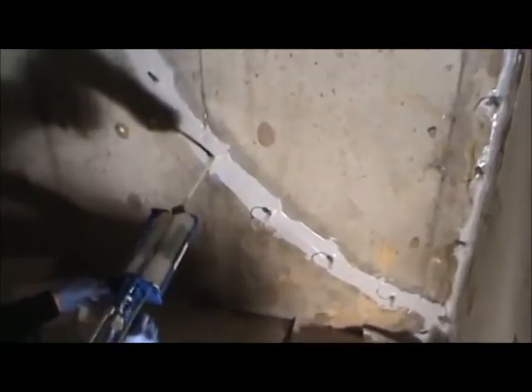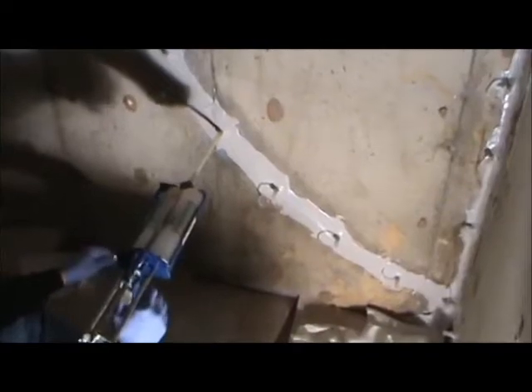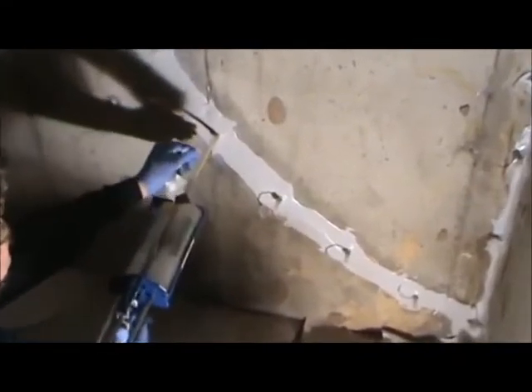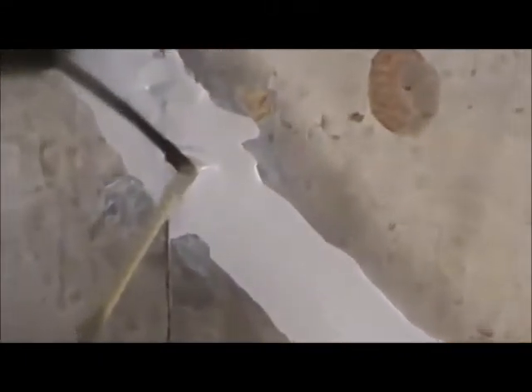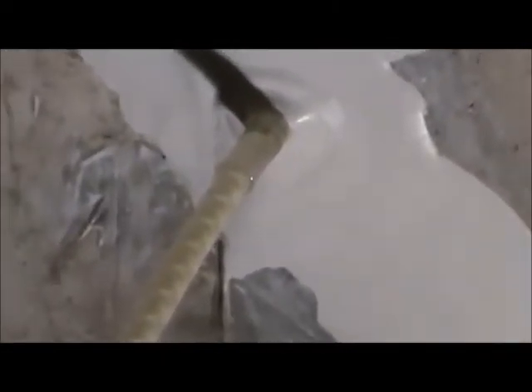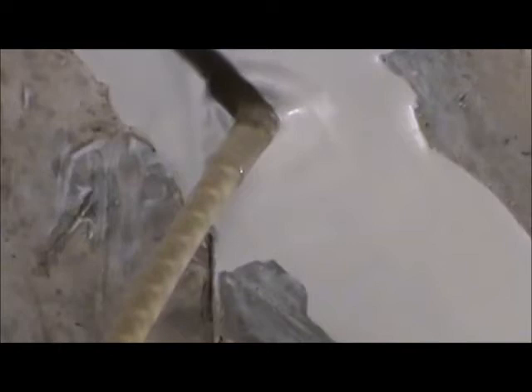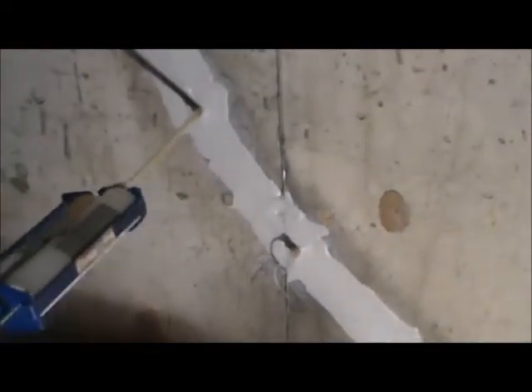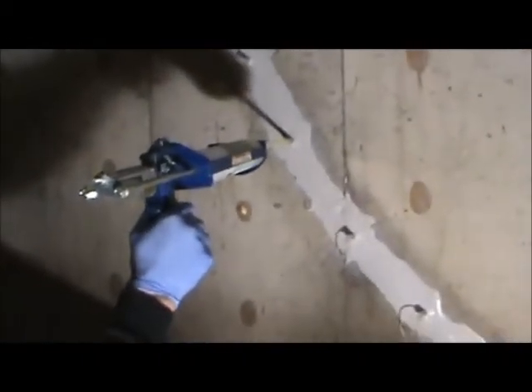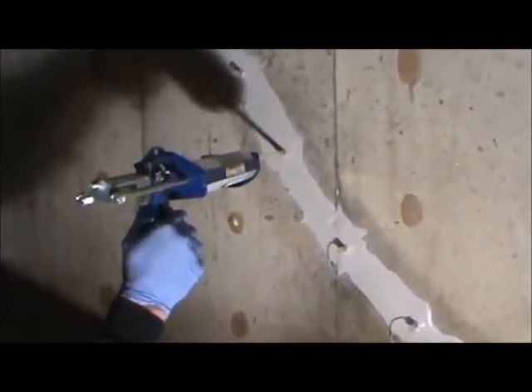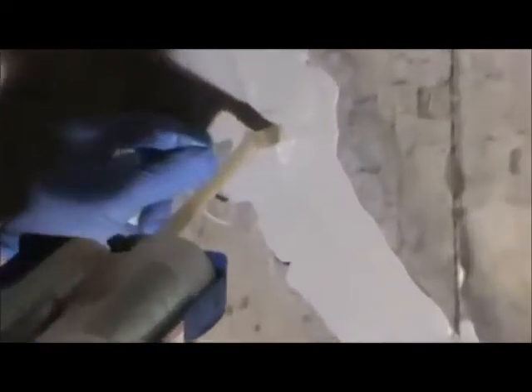Residential concrete has a compressive strength of around 3,000 psi with an internal bond strength of under 400 psi. 1001 injection epoxy has a compressive strength over 14,000 psi and an internal bond strength of approximately 1,500 psi. Basically, the area you're repairing will be much stronger than the rest of the foundation.